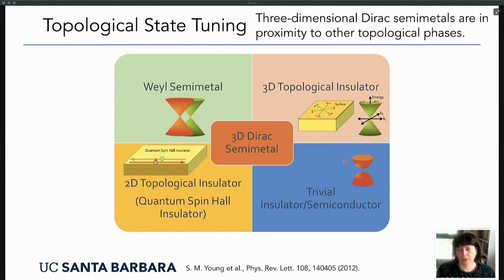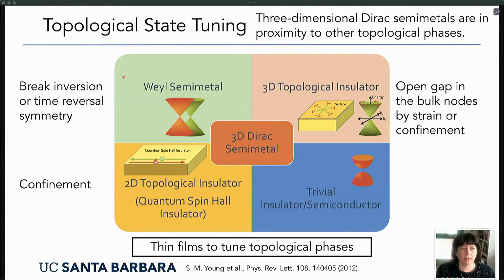You can, of course, also get trivial insulating states. I will not talk about those. If you, for example, break time reversal symmetry or inversion symmetry, and then you split these degenerate Dirac nodes into two, what you get is a Weyl semimetal. Those are also very interesting because, for example, they have their own very interesting surface states, and I'll come back to that.